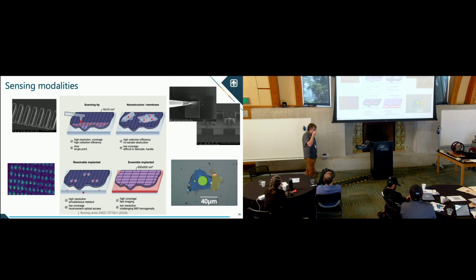Now, one of the easier ways is where you give up on some of the high resolution and just settle with the diffraction limit, or you just collect light from a large area of a sample. This is actually a flake of hBN, hexagonal boron nitride, on a diamond. And there's a lot of NV ensembles below this, and that gives you really fast coverage of your system, and then you get lower spatial resolution. So now you're limited to the micron scale.